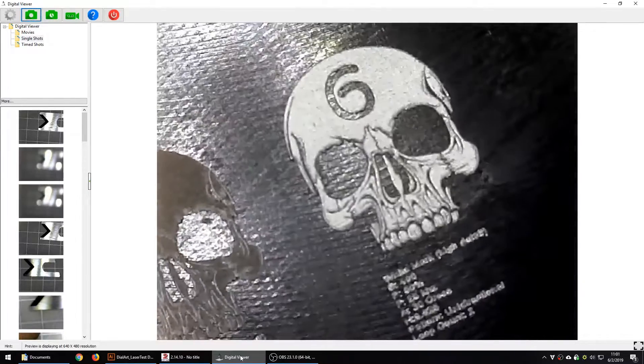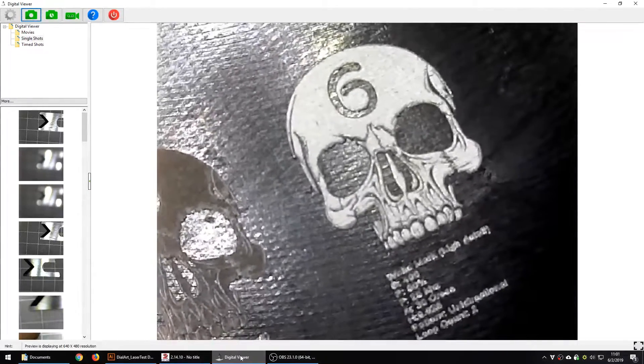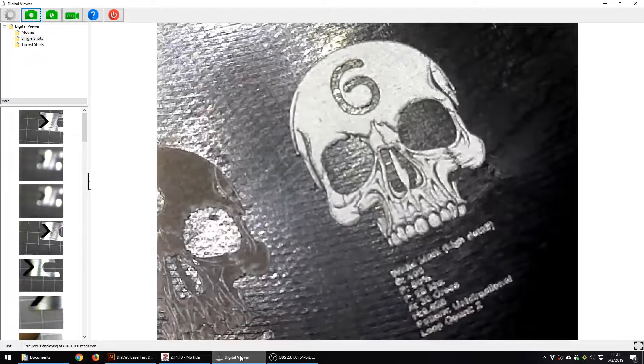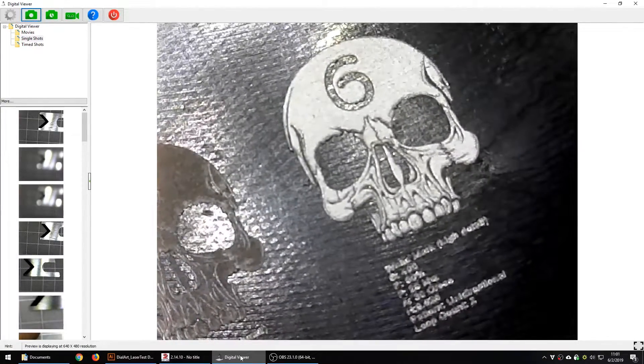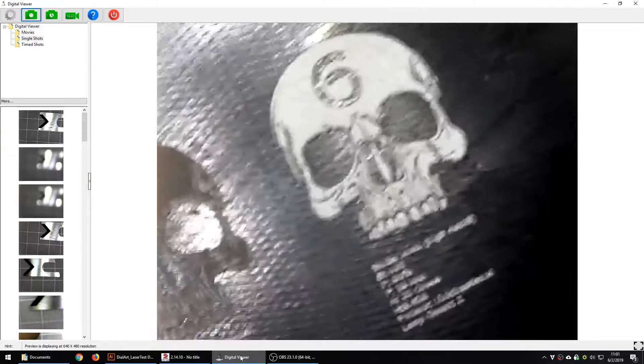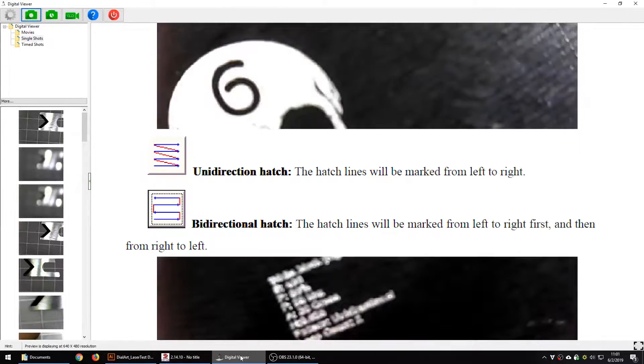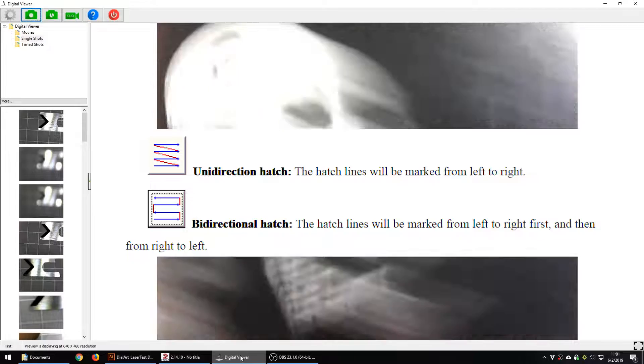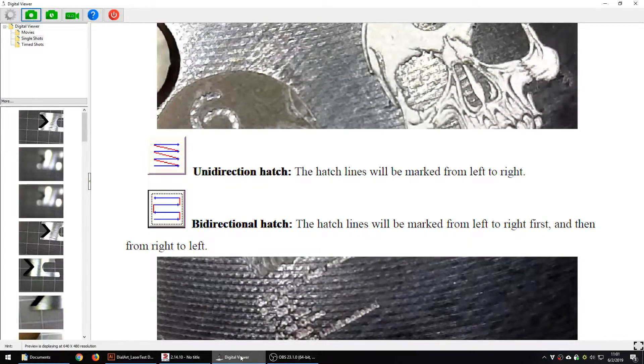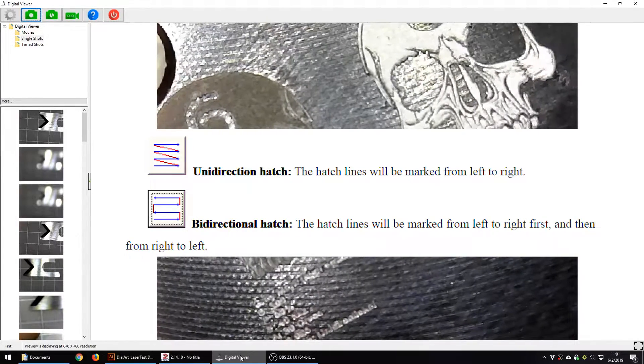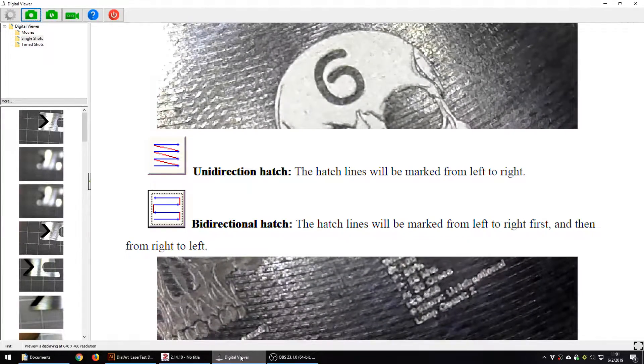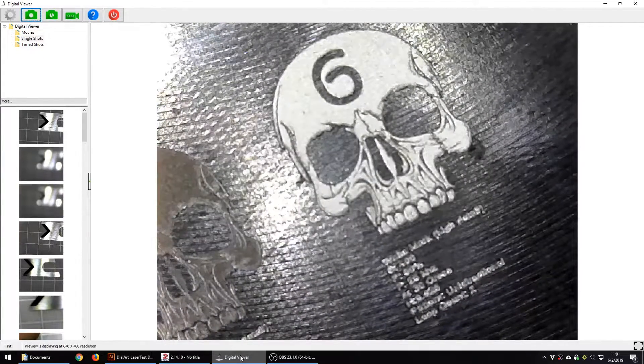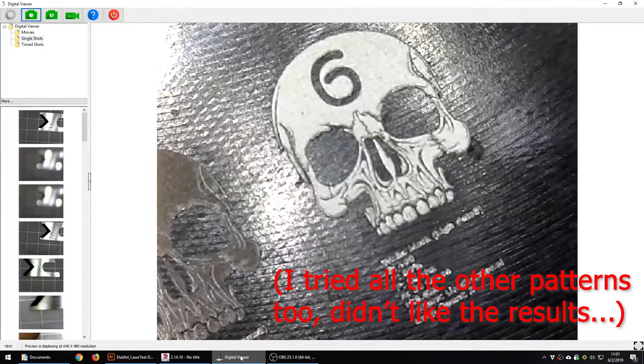You can see it pops pretty well, it's quite white and you can see almost all of the detail, so I'm pretty happy with those settings. The one thing I did change is the pattern is a unidirectional pattern, that means starting from left to right, left to right, left to right. I first tried the bidirectional pattern that goes left to right then right to left and does not connect vertically. That worked pretty well but I found this is maybe slightly better. It takes probably a little bit longer but it looks slightly better.